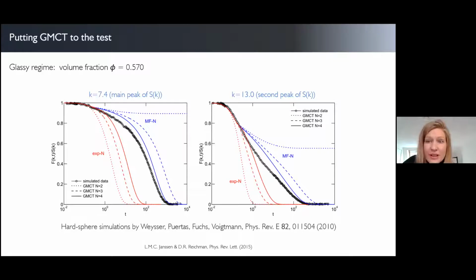And secondly, remember that we still made some approximations in the theory. And so the theory is still not exact. And you can already see here for this wave vector that our theoretical predictions develop some sort of shoulder in the data that is not present in the exact simulation data. So this is an indication that our remaining approximations start to break down here as well. And in particular, one interesting implication of this is, I forgot to mention this explicitly, but one of the main approximations we've made here is that all the relevant structural information of the system is fully contained in the static structure factor only.